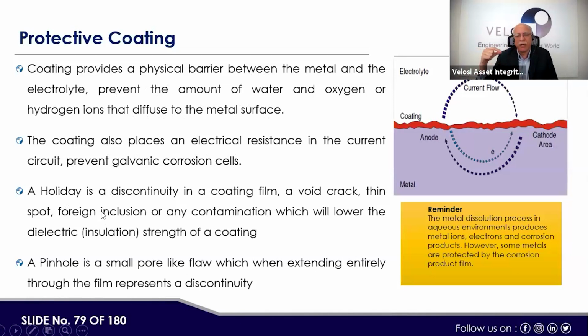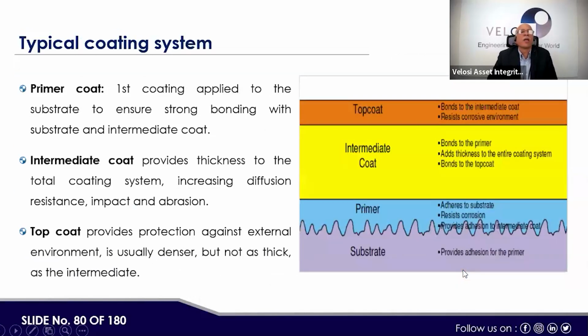A holiday or breakage, or any imperfection, is a discontinuity in the coating film: a void crack, thin spot, foreign inclusion, or any contamination which will lower the dielectric strength of the coating. A pinhole is a small pore-like flaw which, when extending entirely through the film, represents a discontinuity. See here, the metal dissolution process in an aqueous environment produces metal ions, electrons, and corrosion products. However, some metals are protected by the corrosion product films. Now, regarding types of coating systems, we should know that there is a primer coat, intermediate coat, and top coat. These are three coats. If you see here, the primer is on the substrate, basically a steel pipe, and then the intermediate coat and top coat. So these are made in three coats to minimize the imperfection in the coating system, so this barrier could act effectively.